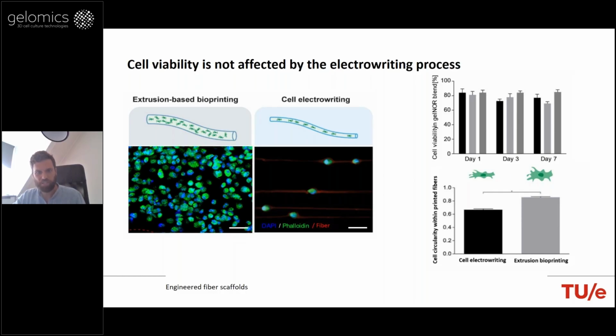It was also interesting to see that we maintained the cell viability high. This was higher for the gelatin-based inks, and there were some changes in cell circularity within the cell electrowriting, which tells us that there were shearing forces stretching the cells, without altering at the cell level some aspects that we don't want to alter, but this of course requires further understanding. But what you see is that you can print with living cells, cell viability is high, and somehow, by shearing the cells, we are aligning them.